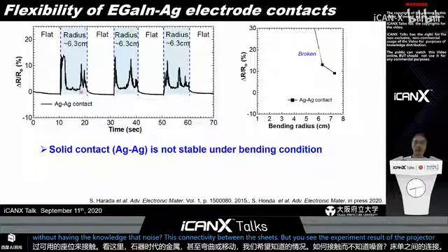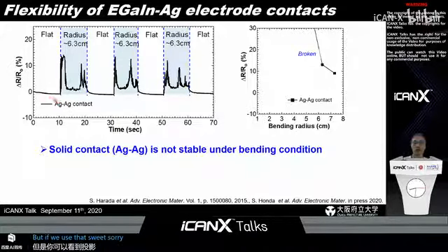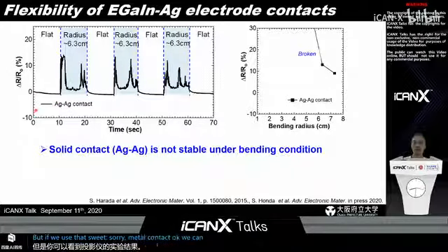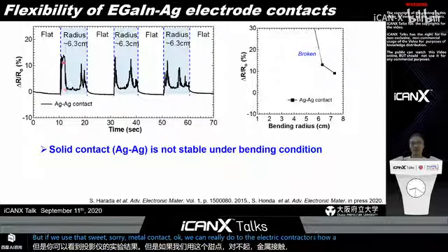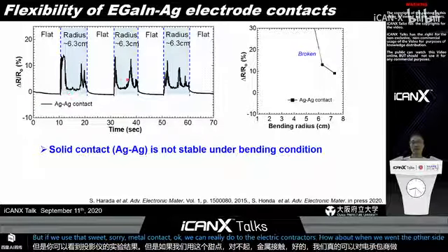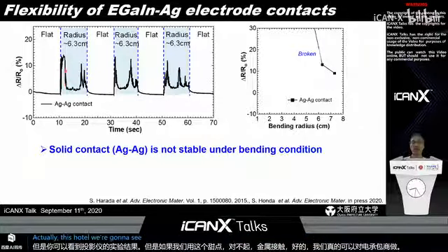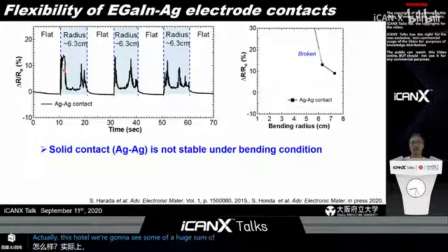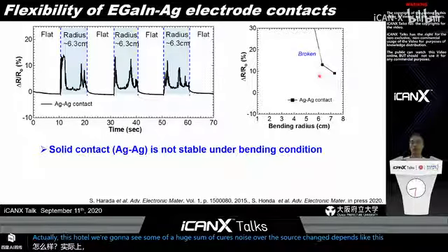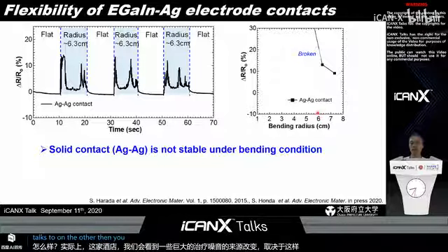So this is the experiment result of the connector. If we use a solid metal contact, we can realize a very good electric contact resistance. However, when we bend the substrate, with this structure we can see some huge noise of the resistance change like this, and also in this structure under a bending radius of less than 6 centimeters, the electrical connection is broken.